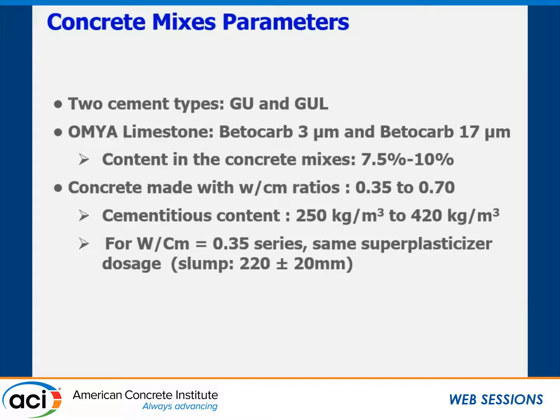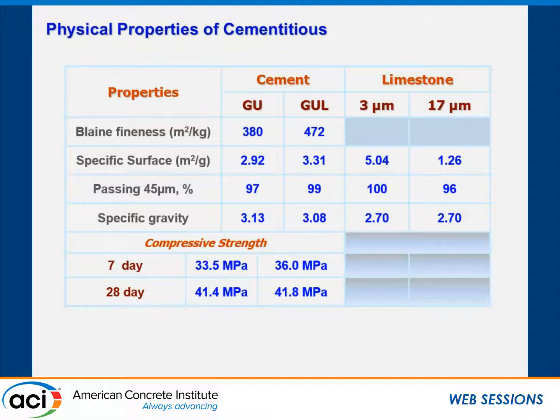Cementitious content varied between 250 kg/m³ (about 420 lbs/yd³) and 420 kg/m³ (about 700 lbs/yd³) depending on the target water-to-cement ratio. He was shooting for about an 8-inch slump. The Blaine for GU Type 1 cement is 380 m²/kg. The GUL is ground finer because equivalent performance is the key — it has a higher specific surface, better 45-micron passing, but a slightly lower specific gravity than regular cement.